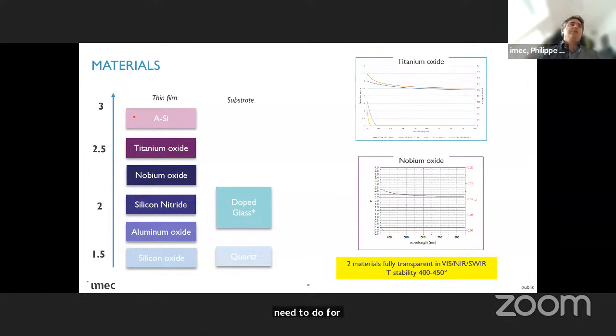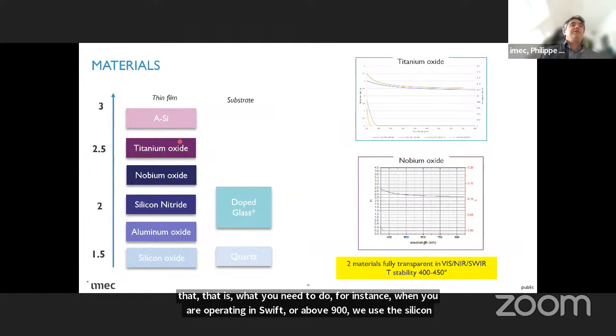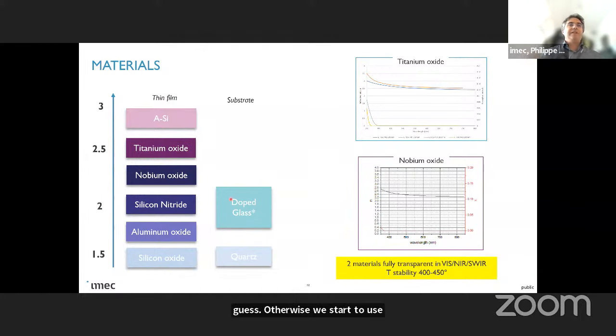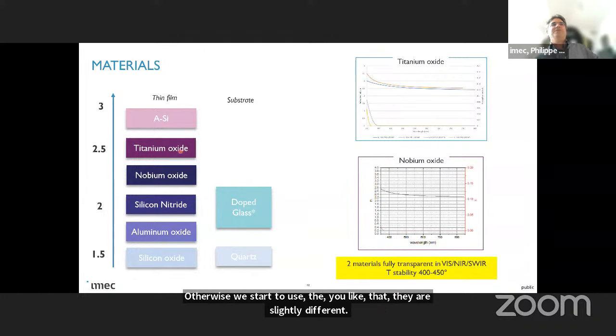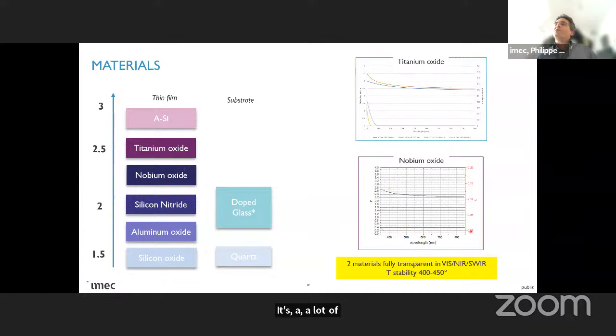We use the silicon because it has the highest index. Otherwise, we start to use a material like titanium oxide and niobium oxide. They are slightly different. There is perpetually a lot of debate in IMEC on why we should use one and not the other one. And to cut a long story short, niobium oxide might be a bit lower in index, but actually is much more stable when it comes to temperature. And titanium oxide can still buy you some performance if it's processed in the right manner.